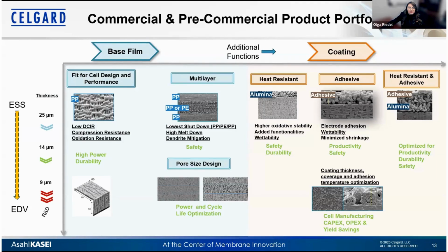At Celgard, we have a variety of thickness ranges between 25 micrometer down to 9 micrometer for the base film. Our wet polyethylene processed wet processed hyper separators from our sister company can go as thin as 4 microns today. In the energy storage space, most of the cells utilize separators that are somewhere between 20 micron to down to